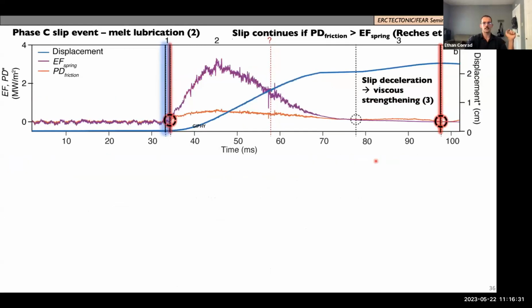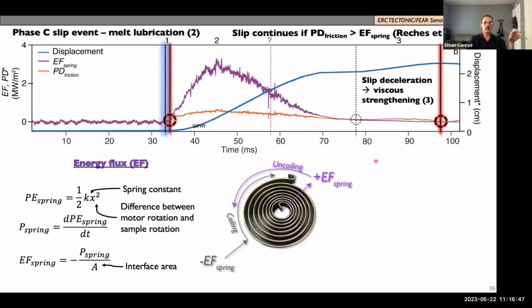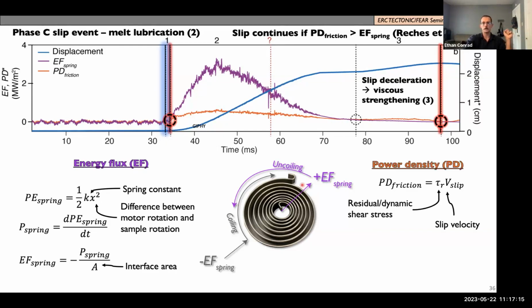Okay, changing it up a bit here to talk about the next steps, thinking more about the energy fluxes. So as we said, slip continues if the power density dissipated by friction is greater than the energy flux provided from the spring. Again, the energy flux is calculated from the storing of spring potential energy and how it's supplied to the interface. If the spring is coiling, the energy flux is negative in our sign convention, just because it's accumulating energy, and it's positive when it's releasing. So when you see it go up, the spring is uncoiling and energy is being supplied to the interface rapidly. And then the power density is simply the sliding shear stress times the slip velocity. So this is the power over the area that's dissipated by friction.